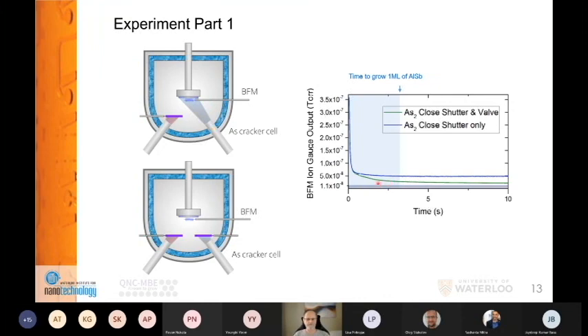So if we close it completely, it still decays, but there's still a long presence of arsenic there. And so we know the flux of arsenic, but we can't speculate how much of this will incorporate into the aluminium antimonide.